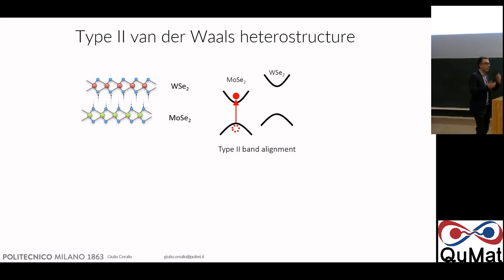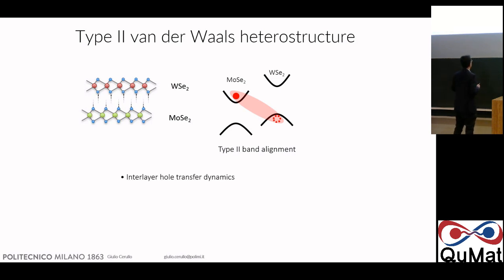But now you know that the hole always tends to float to higher energy. So what will happen is that the hole will have a very rapid transfer to the other material, and you will form what is called an interlayer exciton, where now the electron sits on one material and the hole sits on the other. And this has completely different properties. It has much longer lifetime. It can be transported over a distance. So it's a very interesting object. So what we want to do with our experiments is visualize this process in real time, and study the interlayer transfer dynamics.